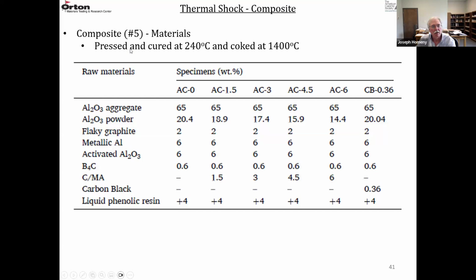So these are the materials they looked at. They're all pressed. The resin was cured at 240 degrees C, and they were then coked at 1400 degrees C. So it goes from AC0 to AC6, and then there's one with carbon black. This happens to be a nano carbon black addition at 0.36%. So the Al2O3 aggregates were all in the 65% range. Metallic aluminum was 6%. Flake graphite was 2%. Fine particle size alumina, which is reactive alumina, 6%. They had B4C for an antioxidation agent at 0.6%. And then the phenolic resin was held at 4%.